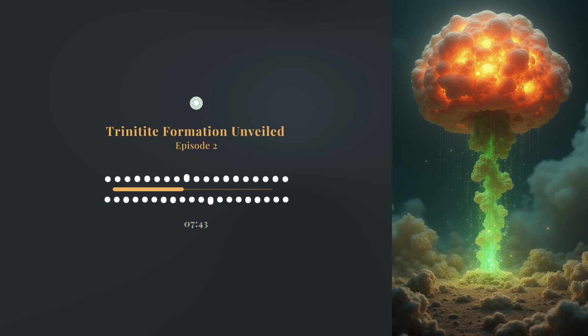Amazing. Okay, visually, we usually think of Trinitite as green, right? Is that always the case? Green is definitely the most common color, yeah. That typical greenish tinge. But there's another famous type, red Trinitite. Red? Where does the red come from? That color comes from copper. The analysis traced it back to the copper wires that were part of the test setup connecting the bomb to the diagnostic instruments and firing circuits. They got vaporized, too. So the color itself tells you something about what specific materials got caught up in the blast. Precisely. And besides the green and the red, you find different forms, too.